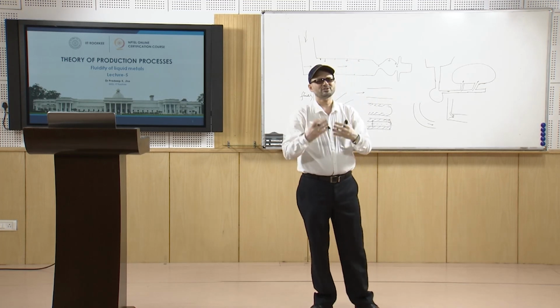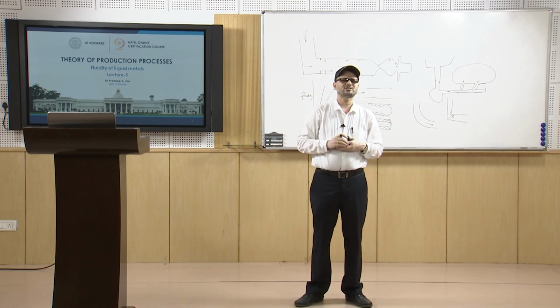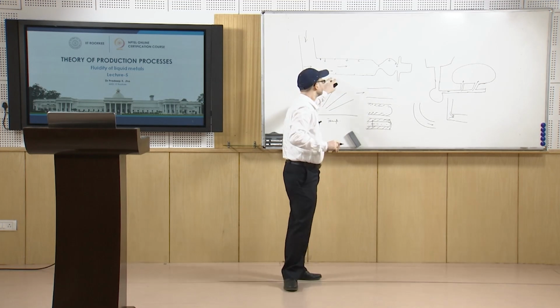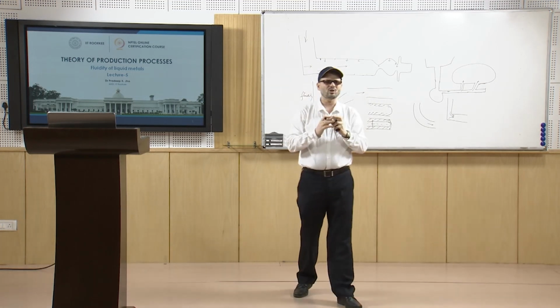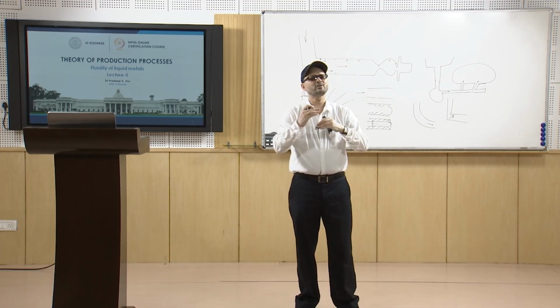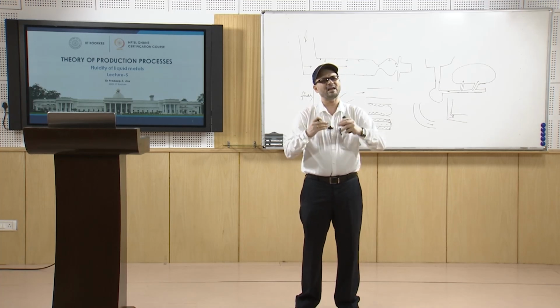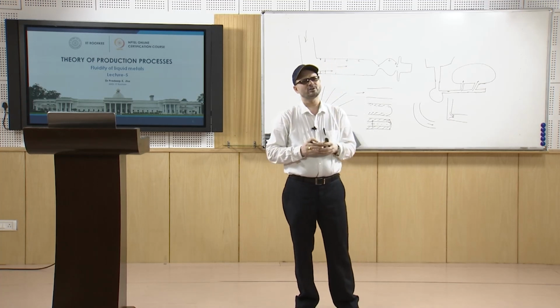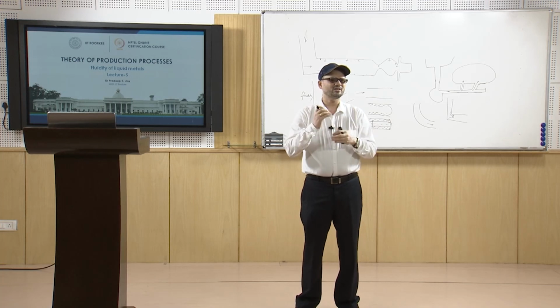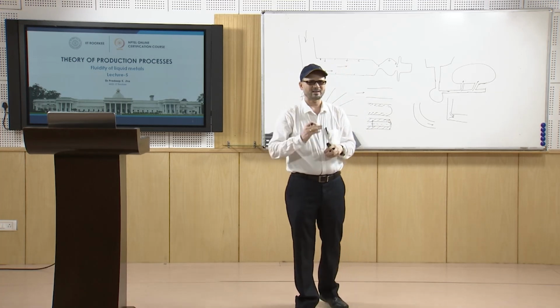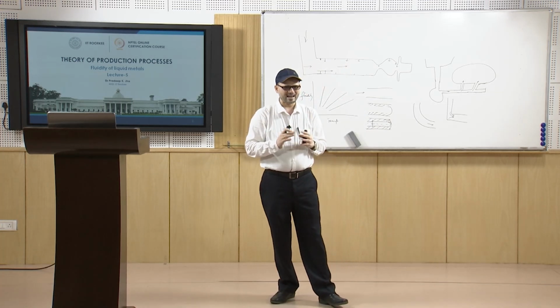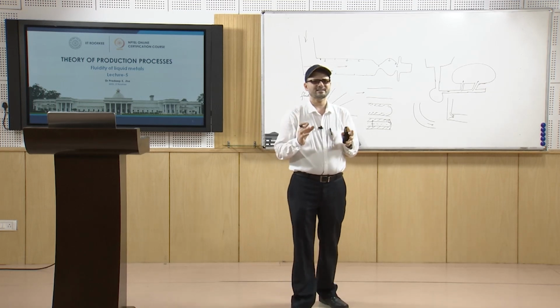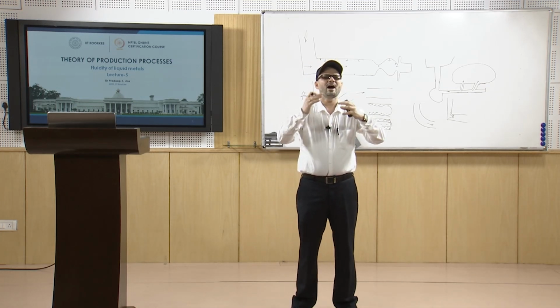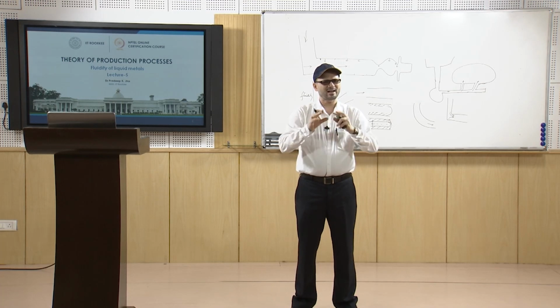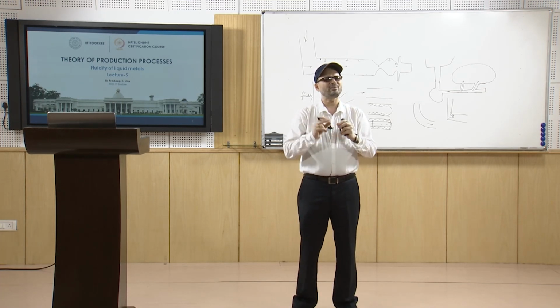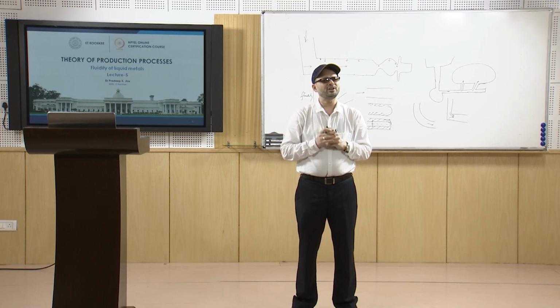So, if you are giving some temperature to the mold, you ensure that the superheat is not lost quickly. Many a time we increase the mold temperature, because that reduces the chilling effect. The temperature which comes down quickly is not experienced. In that case the fluidity will be higher. So, these are the different factors which affect the fluidity of the material.